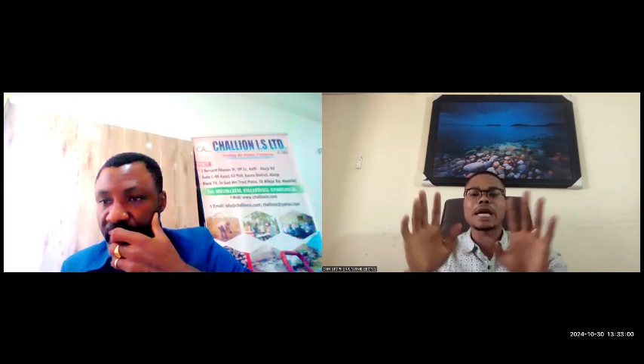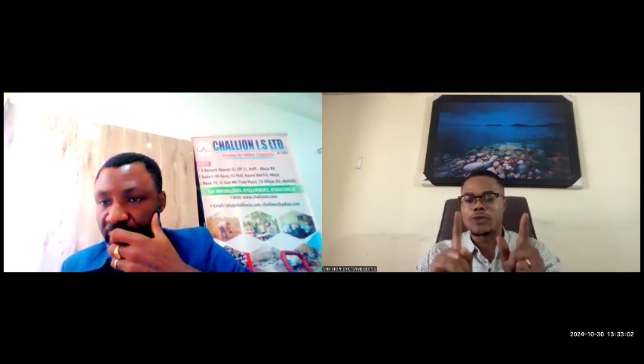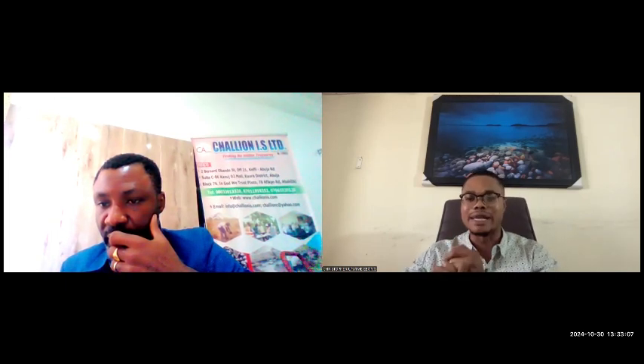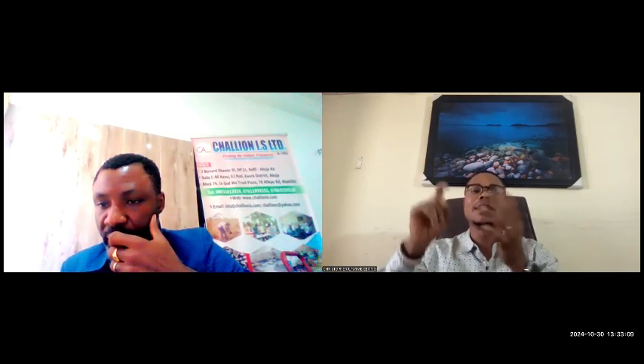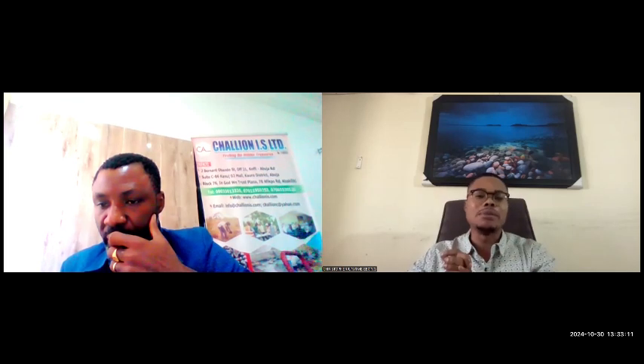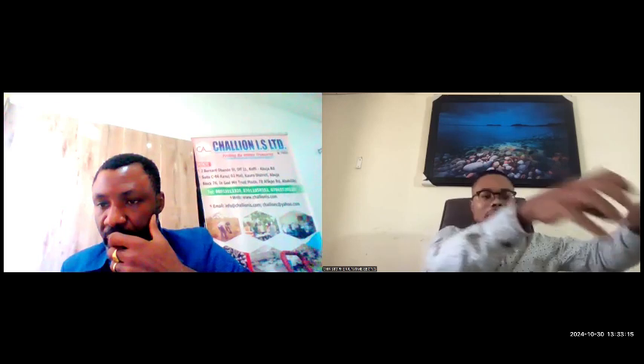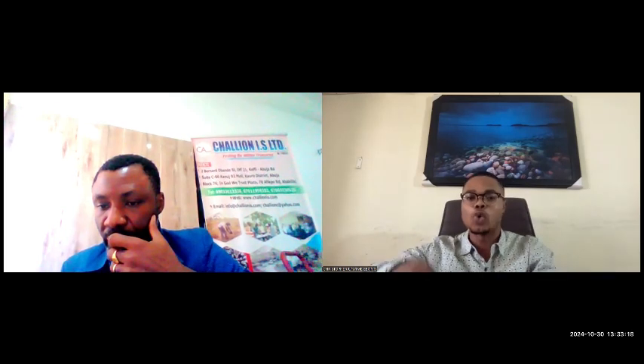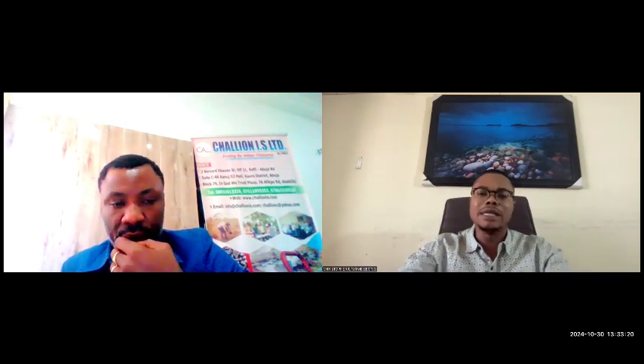And then for monazite, the best approach is in 2 ways. It is in 2 forms. One, you can determine the concentration of monazite as monazite grade. That's why they say 80% monazite, 90% monazite, 100% monazite. That is grade determination, and that is done through what we call gram scale. You take a certain known quantity of the monazite, and then you use your magnet to remove the other materials that can be attracted by magnet, and then you weigh the remainder and get the final weight.